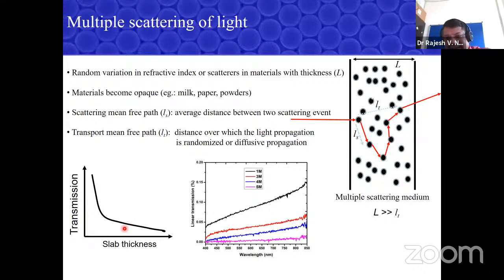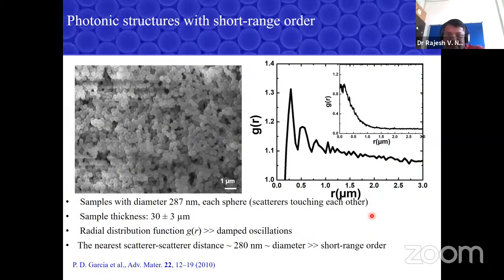And the scattering length scales, instead of Bragg length in a photonic crystal, we talk about scattering mean free path and transport mean free path. And if this transport mean free path is much less than the sample thickness, we say the light propagates diffusively. Okay, so I'll use these numbers later in my slides. That's why I just put in one slide to tell you about these. Because if you have a disordered medium, to characterize your disordered medium, you need to measure those numbers, the scattering and the transport mean free path, and there's a way to measure it.